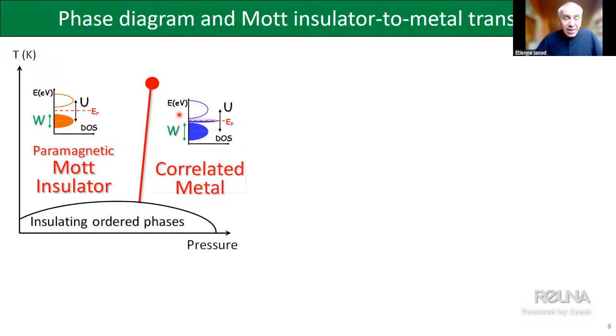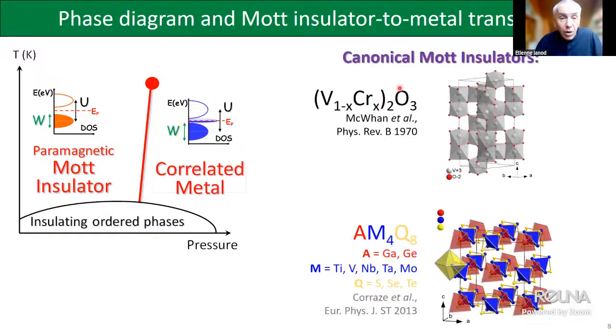Right. In fact, let me mention here a few examples of real systems that really illustrate this concept and this reality of Mott insulators. Among them, we can cite the V2O3 system doped with chromium, which has been studied for more than 50 years. But also, I would like to cite another family, no longer an oxide, but a chalcogenide system. Q is indeed a chalcogen such as sulfur, selenium, or tellurium, and this family AM4Q8 we have studied. You will see some results that we obtained on this system.